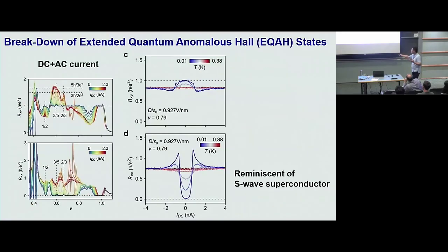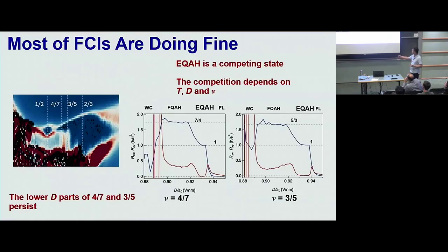I seem to be telling you that at lower temperature, FCI is gone. However, that's not true, okay? So this is a zoom in on that region. 2/3 is supposed to be here, and in this particular device, you couldn't tell 2/3. But for 4/7 and 3/5, you actually can see that now the vertical stripe got cut into two parts. The higher displacement field part becomes the integer, while the lower displacement field part is still there.